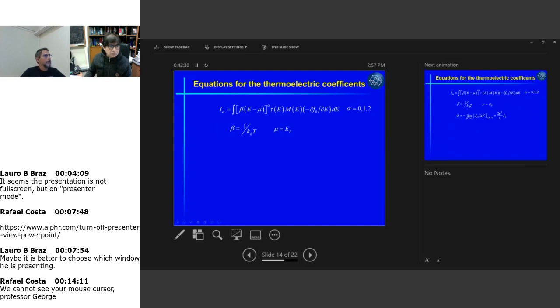So if alpha is equal to zero or alpha is equal to two, all the terms in this equation are positive. But if alpha is equal to one, which, as you recall, is for the Seebeck coefficient, then this could be positive or negative depending on whether the energy is below or above the chemical potential. So the Seebeck coefficient can take positive and negative values. It's positive when the transport is through holes and negative when the transport is through electrons.